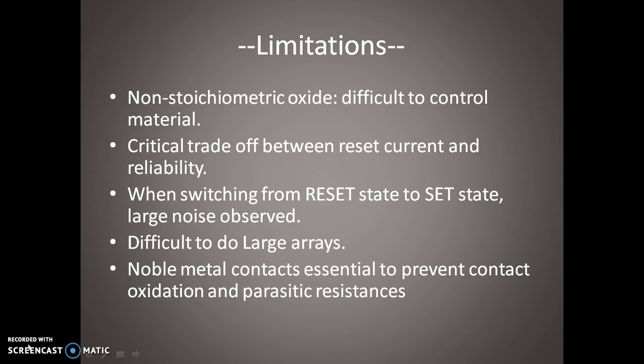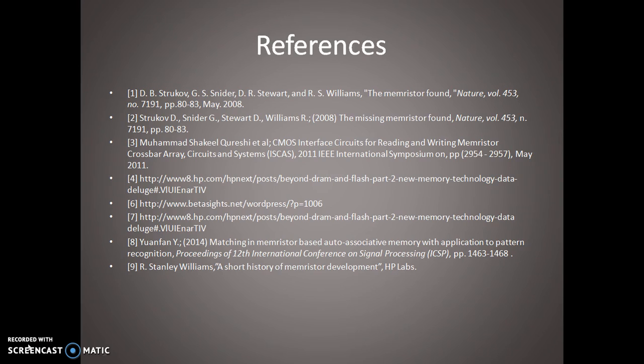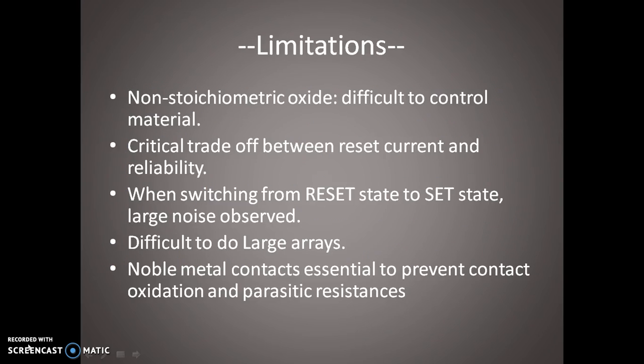Now, talking about the limitations of memristors. The first thing is that the non-stoichiometric oxide is difficult to control and there is a huge trade-off between reset current and reliability. When switching from reset state to set state large noise is observed. It is difficult to make large arrays of these memristors and hence this limits its probability of replacing flash and DRAM memories in near future.